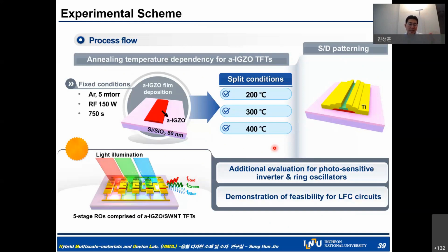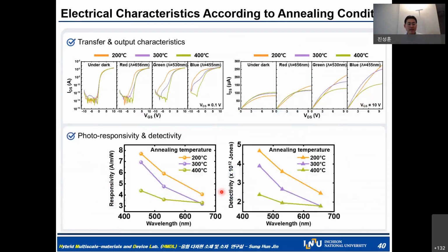So in order to achieve scalable properties as well as different photodetectivity, we achieved the n-type region from the indium gallium zinc oxide, just by changing the annealing temperature to control the oxygen level. However, the p-type region, the carbon nanotubes, is fully adapted to achieve the light insensitive property. With this kind of scheme, we fully validated the different annealing temperature effect as well as the wavelength dependent detectivity properties nicely secured here.